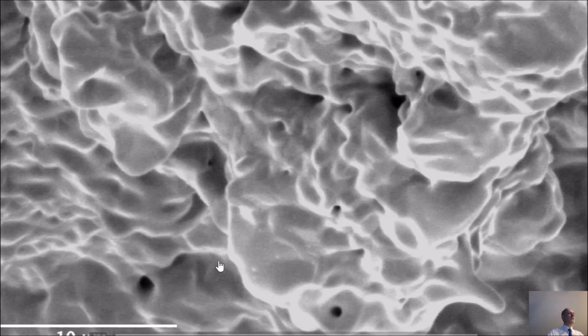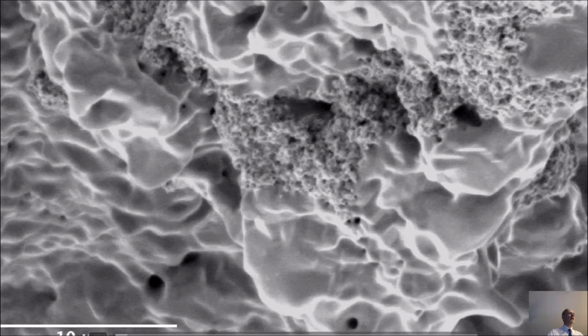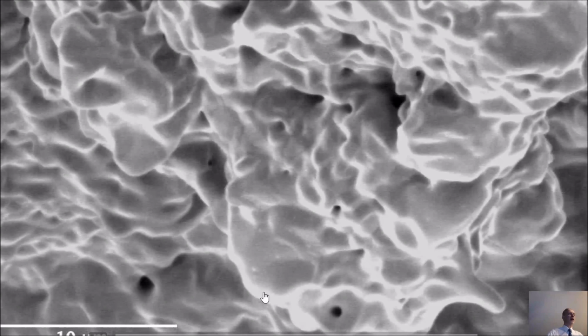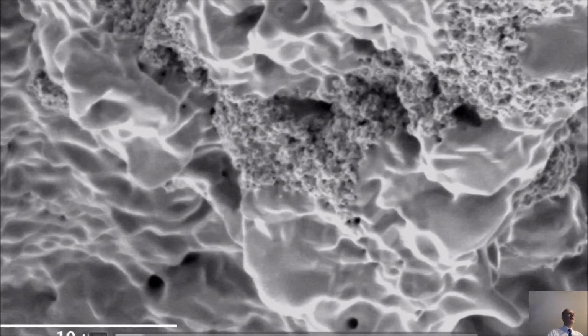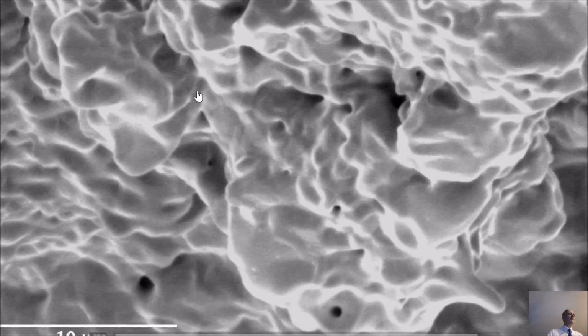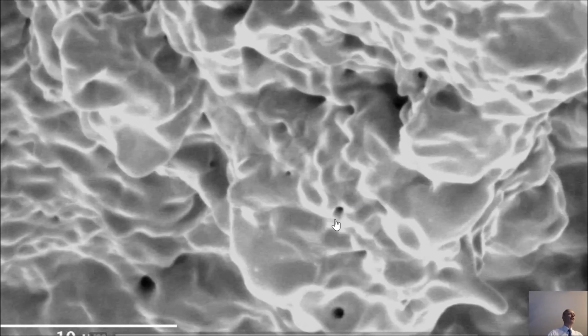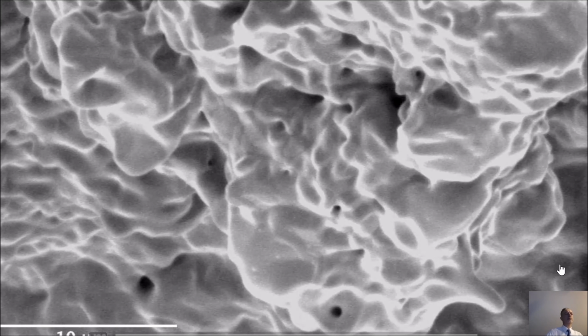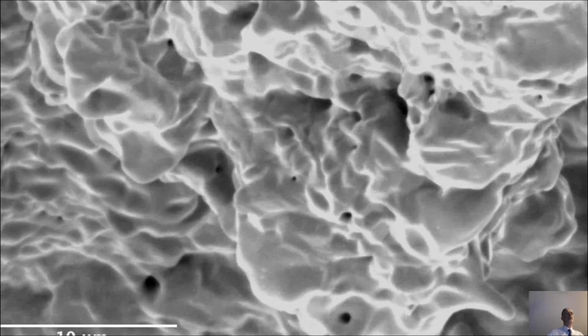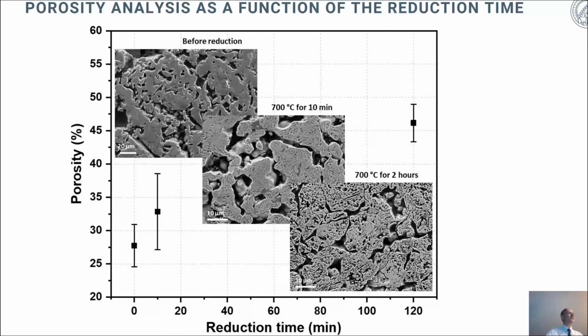Here you can nicely see when he exposes such a pellet directly inside the electron microscope to hydrogen, as is shown here, then you can see how this relatively smooth iron film really forms on top of the wüstite. That means you build up this certain barrier of iron through which both the hydrogen and the oxygen must diffuse.